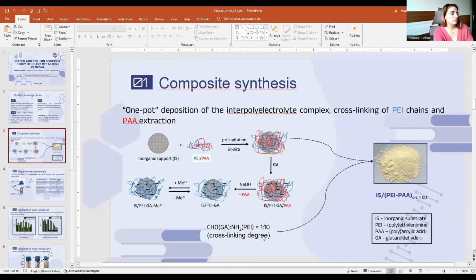So the synthetic composite involves one-pot deposition of an interpolyelectrolyte complex between polyethyleneimine and polyacrylic acid. We can see in the picture the schematic representation of the synthesis, and we cross-link at a lower degree, at 0.1 cross-linking degree, and in this way we obtain the sorbent that we want to test.